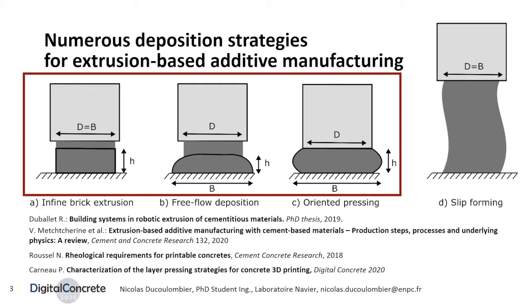In the first strategy, called inline brick extrusion, the shape of the layer directly relates to the nozzle geometry. The material yield stress at the nozzle needs to be sufficiently high for the layer to remain undeformed after deposition. In the second strategy, called free flow deposition, the layer shape results from a competition between gravitational force and yield stress. These two deposition strategies were previously studied by Roussel.